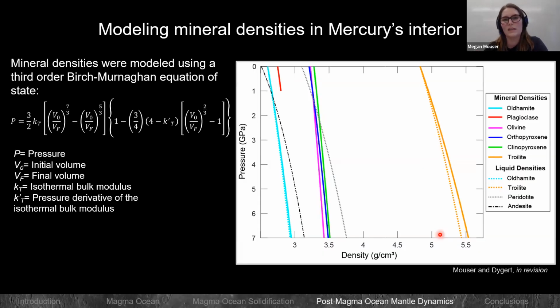So we started with modeling the densities of the different types of minerals we would expect in Mercury's interior using the third order Birch-Murnaghan equation of state. So we're looking at our silicate minerals again, the olivine, orthopyroxene, clinopyroxene, but we're also introducing sulfides into the mix because now, again, we want to consider what is the influence of the sulfides within the interior. So we have our calcium sulfide, oldhamite, over here. It's less dense than our common silicates. And then we have troilite, which is an iron sulfide, and that's representative of basically the upper bound in terms of the density difference between the sulfides within Mercury's interior. And it is quite a bit denser than our silicates.